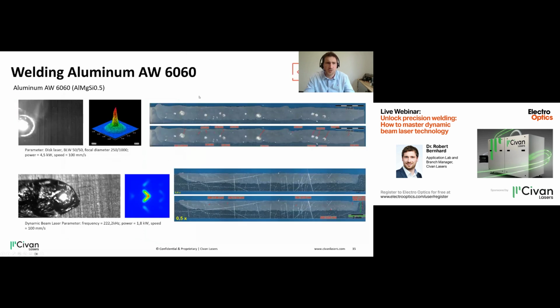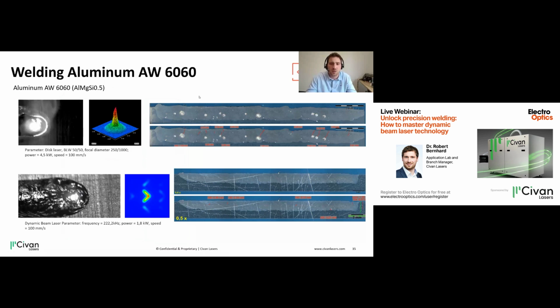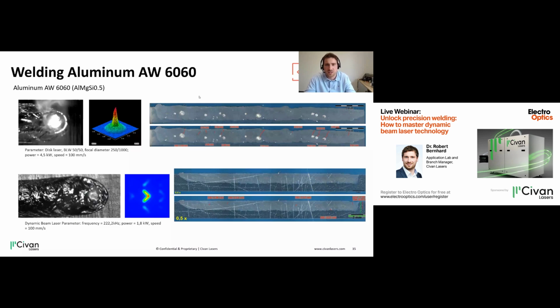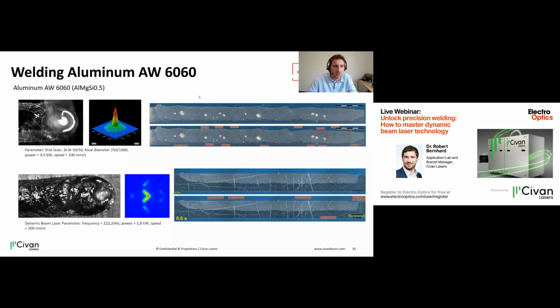This also is true for 6000 aluminium. Here we usually have problems with porosity because the keyhole collapses quite frequently. Even at lower speeds, you can see on the left side that sometimes the keyhole collapses and then we have a pore inside the material. And this is even though we are comparing to a static ring laser.